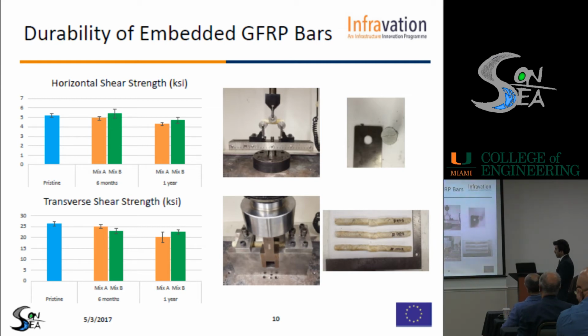And then you go to the transverse shear. So for transverse shear, you have a bar, and then you apply your load at the midspan. And as you see again, this is a pristine bar. At 6 months, it went down, but it's still comparable.